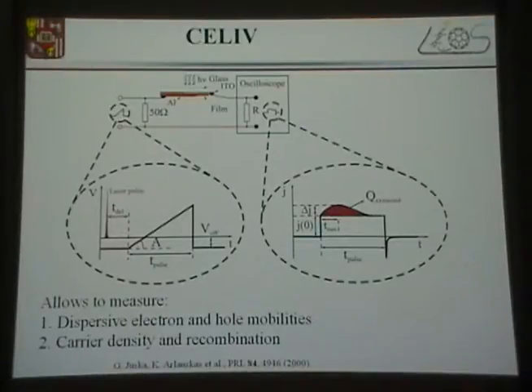But the basic setup is actually very, very simple. We don't need anything except the oscilloscope, maybe a laser, and the sample, in principle that's all. What you do is you apply a triangle shape, a ramp voltage pulse at the input, and you measure the so-called RC circuit, as it's called in electronics, where R is the resistor and C is the capacitance. Your sample is the capacitance, and the resistance is in the oscilloscope.